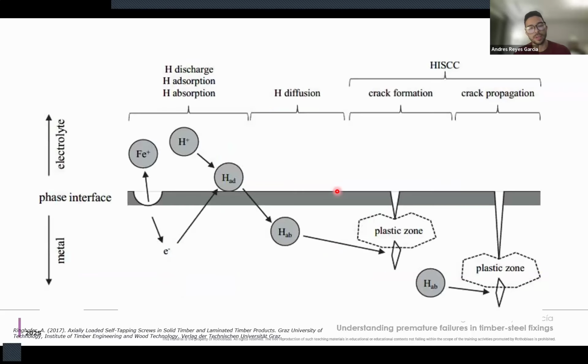This happens from days to weeks after installation. This is more or less a chemical explanation of what happens. I won't go too much into details, but we need a force and we need some corrosion happening. As a byproduct of the corrosion, we create some hydrogen that gets into the first and most external layer, and it will be absorbed to the inside of the section of the fastener, and then, in the presence of a discontinuity of the coating, it will induce crack formation and crack propagation, and then with the sum of different cracks, it will lead to failure.